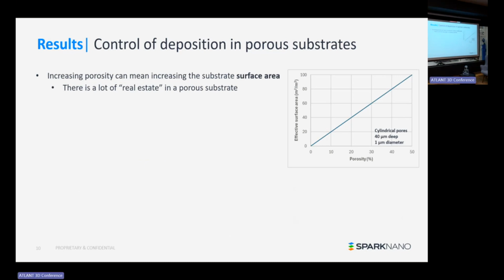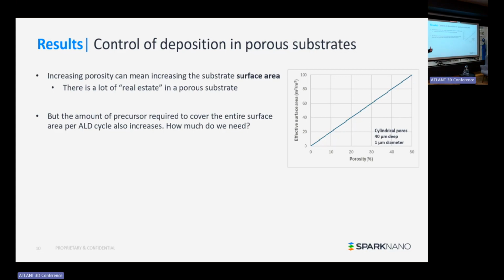And one thing that happens if you increase the number of pores is that you increase the porosity, but you can also increase the surface area, the effective surface area, in terms of square meters per square meter. So here I took just simple cylindrical pores of 40 microns deep, 1 micron diameter. I increased the pore density, so the number of pores per square meter, and then you can calculate porosity and effective surface area. You can see that surface area increases quite a lot. So there's a lot of real estate, or a lot of room, inside a pore structure if you count all the way from the top to the bottom, of course. That's the play on the Feynman quote. The consequence is, if you want to coat these structures, you also need to supply a lot of precursor, because the amount of precursor that you need to supply scales with the surface area, of course.